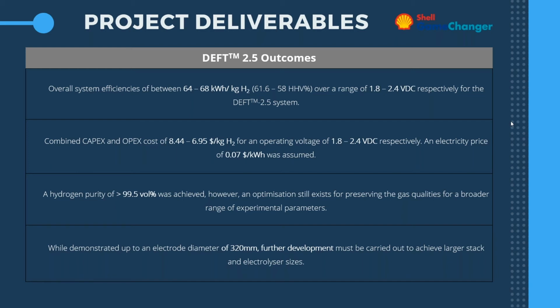And we demonstrated the stack within a voltage range of 1.8 to 2.4 volts. A little bit higher than conventional alkaline electrolysis technology, but we have the aim to bring it into the region of 1.7 to 2 volts in the near future. And regarding the combined capex and opex costs with an assumed electrical production cost of $0.07 per kilowatt hour, we calculated the end cost to produce hydrogen from our system produced at atmospheric pressure to be in the region of about $8.44 to $6.95 per kilogram, depending on where in the voltage range you go about operating. So we feel there's still significant potential to go about improving that cost range.